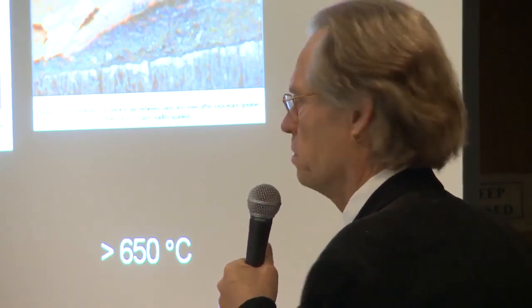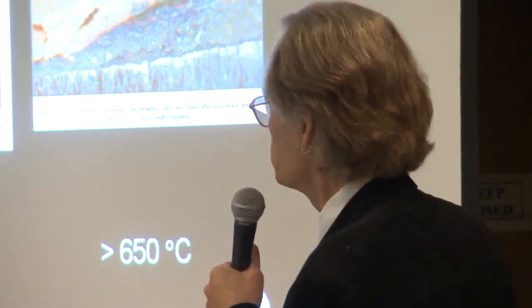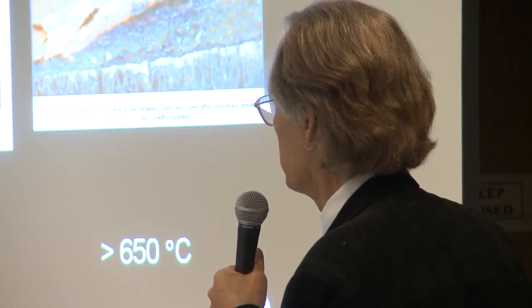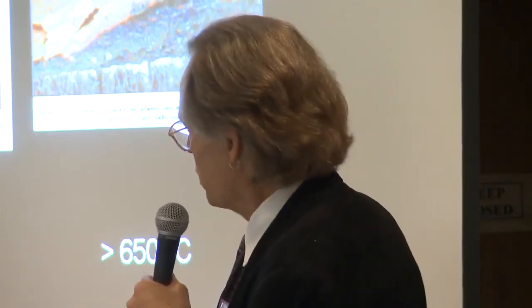And this experiment you can carry on until 800, 900 degrees. I've done it myself, but these are pictures from the NIST report. So from looking at the mud cracking of the paint, they could tell how hot the steel beams had been. And I can tell you as a footnote that they did not find any steel beams that had been beyond 650 degrees Celsius based on this way of measuring.